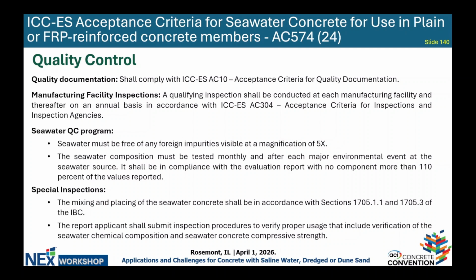So with the initial report, you do an initial qualifying inspection of the manufacturing location, and then we require surveillance inspection every year. The Seawater Quality Control Program, so the composition must be tested monthly and after every major environmental event. And then the seawater must have no foreign impurities within 5 times magnification. Mixing and placing of the concrete should be in accordance with 1705.1.1 and 1705.3 of the IBC. But if there's any special instructions from the producer, that should also be given.